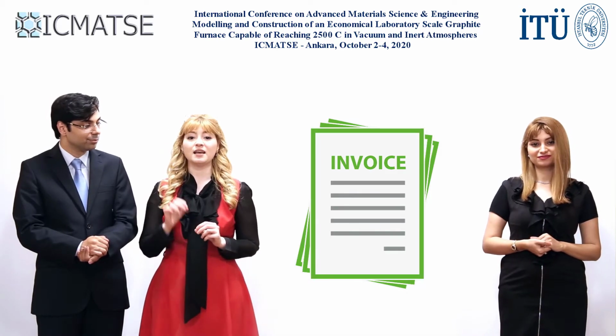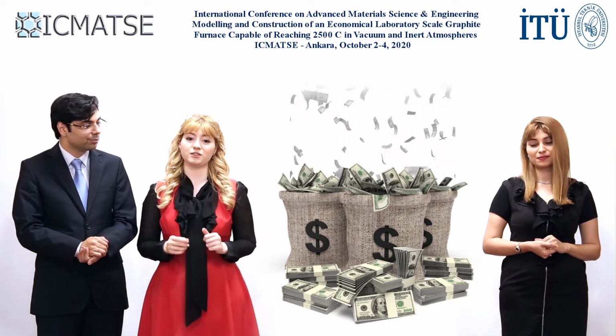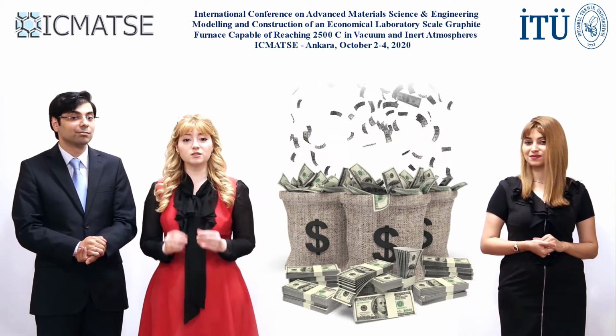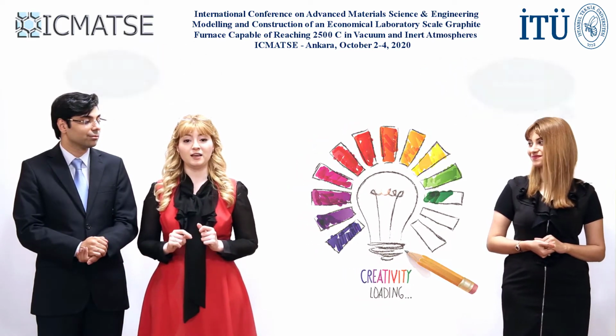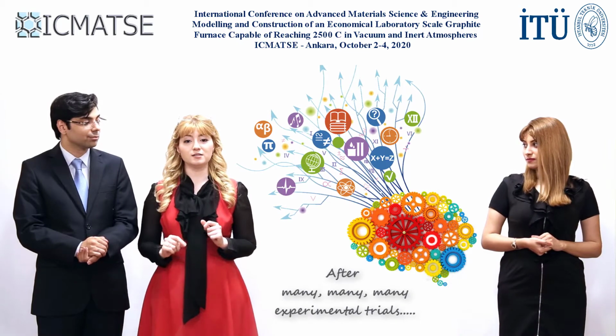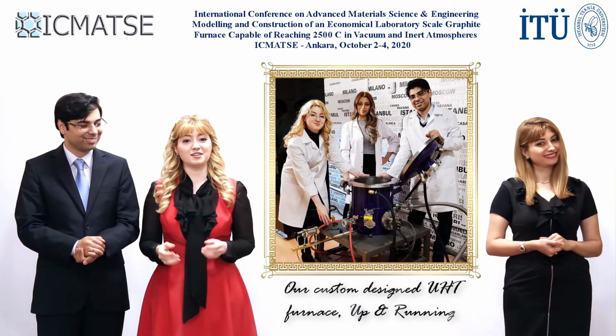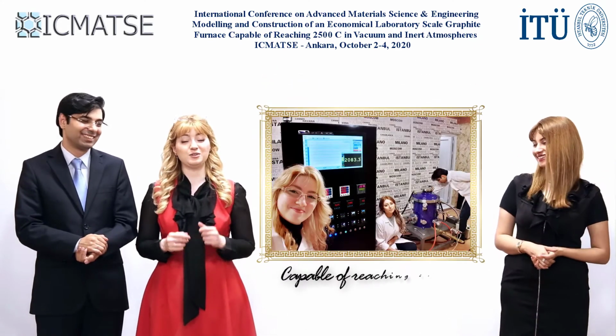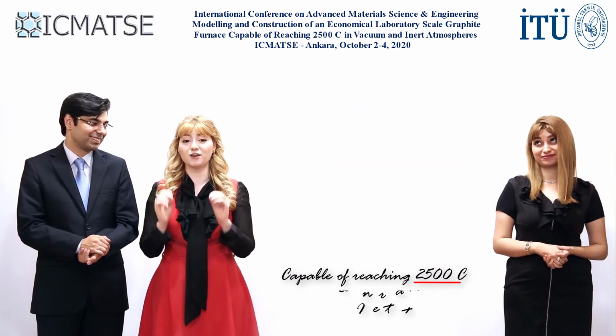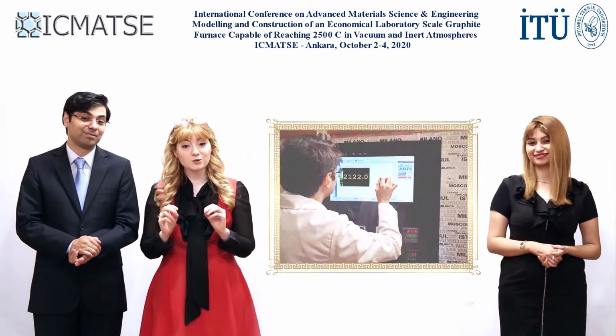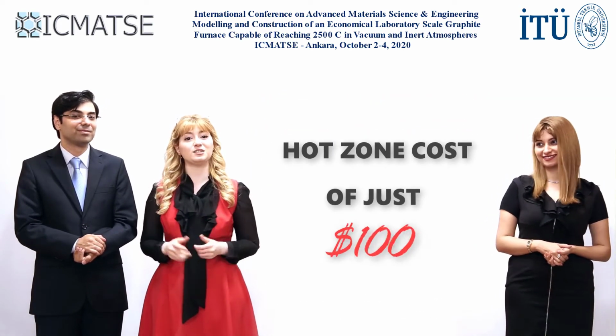We really wanted to see the magical temperatures of 2000 degrees Celsius and above on our PID. So we started requesting quotations from a few companies who specialize in such systems. And to say the least, the prices were just too much for the budget that we had for sintering experiments. So we started to play around with the idea of building our own furnace back in 2012. And after experimental trials, which mostly proceeded as a hobby, we now have a magnificent furnace up and running since 2015, which is capable of reaching 2500 degrees Celsius with a hot zone cost of just $100.